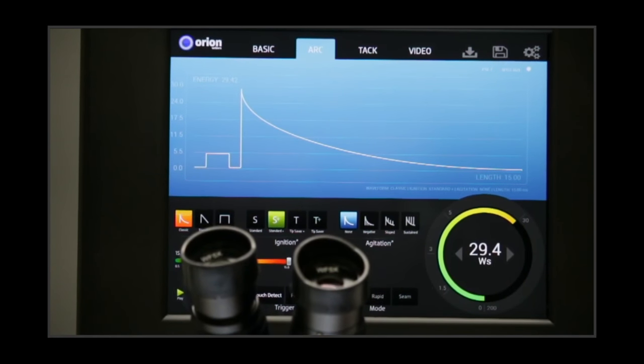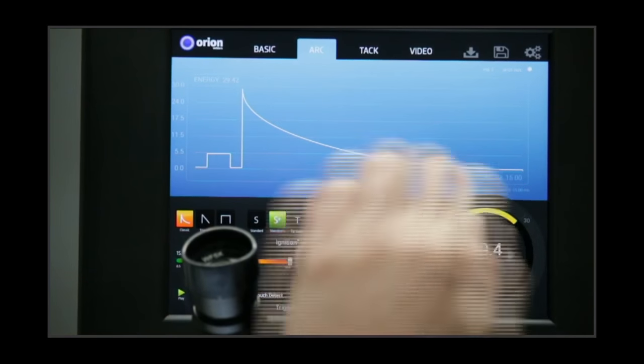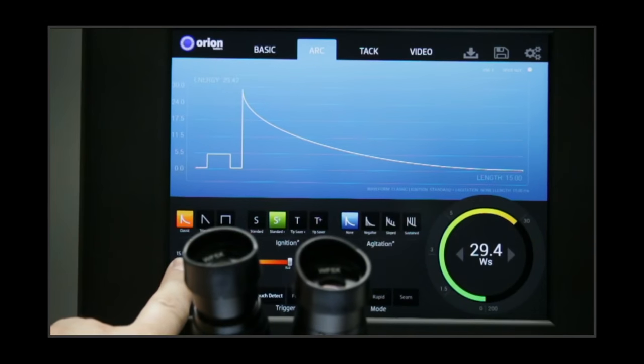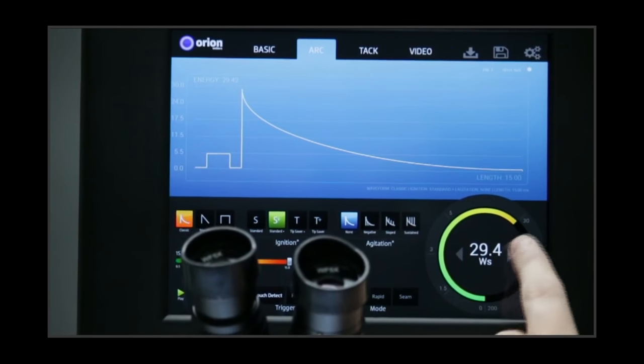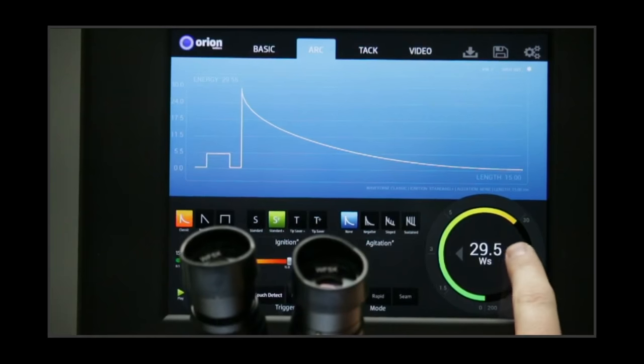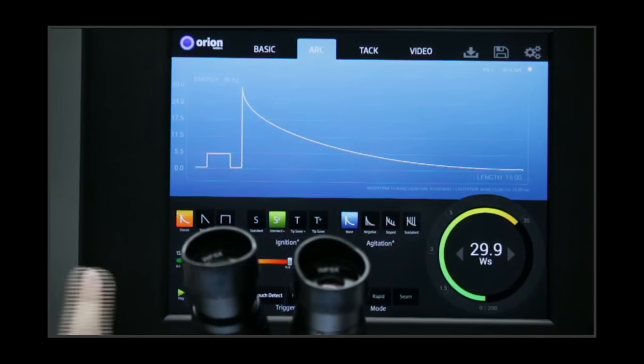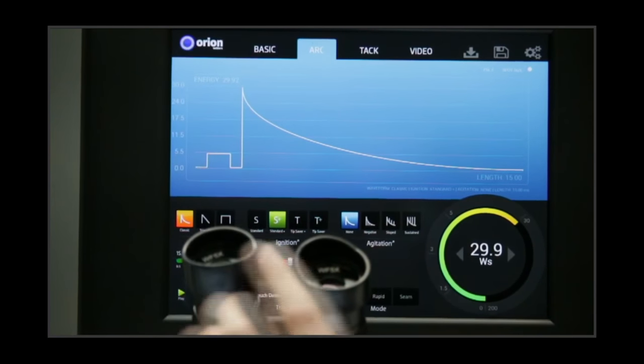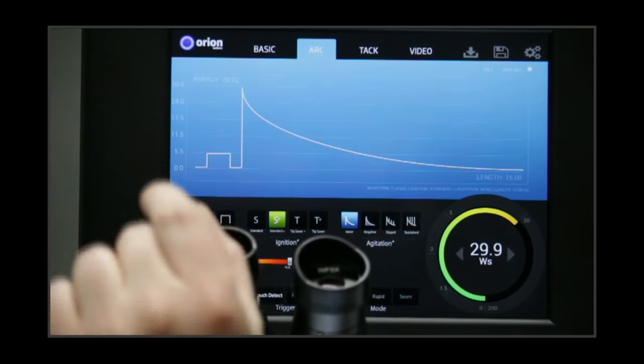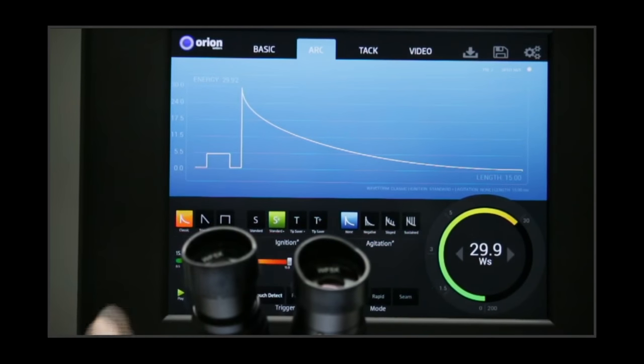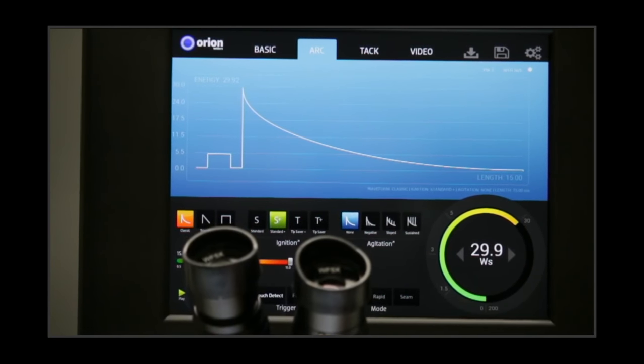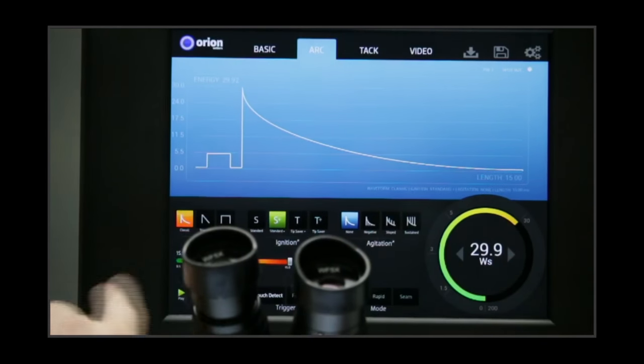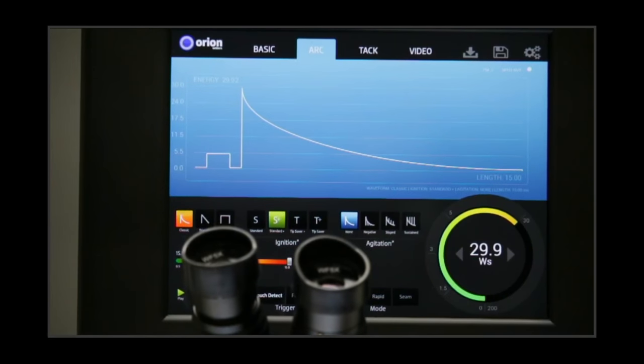One thing to keep in mind, specifically as we work with this, is our weld length. And this may be difficult to see because of the microscope in the way. But here you can see it says 15. And that's at 29.5. If I just slightly increase this, right, 29.9, I got 15 milliseconds. So what that means is that my weld energy is going to be 30, but my weld time is set at 15 milliseconds. One of the tricks with silver is to increase that. Increase your weld time to get a longer weld length.